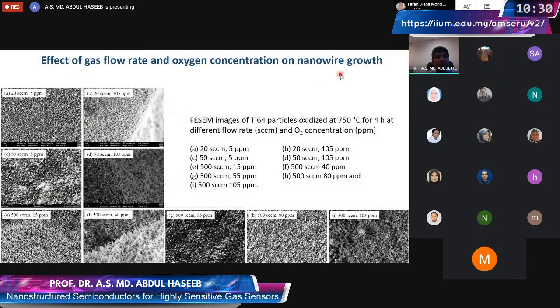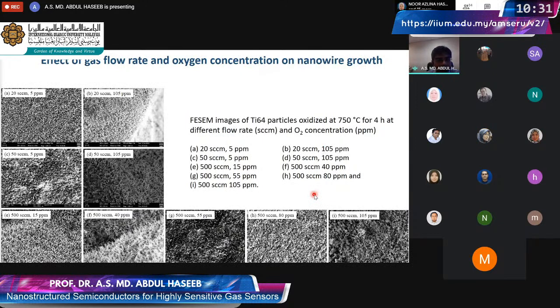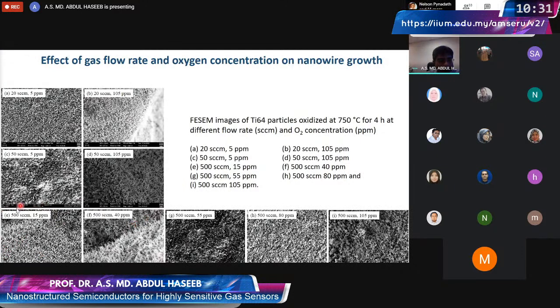This shows the combined effect of gas flow rate and oxygen concentration. I just remind you, we use a carrier gas, which is argon, and then we add a little bit of oxygen, because these nanowires grow in oxygen-deprived environment. And we varied the concentration of oxygen from 5 ppm to 105 ppm. And the flow rate was varied from 20 standard cubic centimeter per minute to 500 SCCM. And as you can see, there is, again, a narrow window where we can get some nanowires. And that window is about 500 SCCM, 15 ppm, 40 ppm. So this is the range.